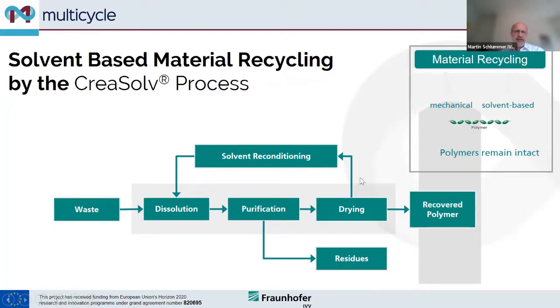Solvents are kept in a circle, and of course, purification means we always have a leftover. Leftover could be something which is not reused, but in our case, we try to make use of that. So if we go with a multi-layer packaging, we first try to get out the polyolefins, PE, then PP. Then we also had it for PA and even for PET. In the automotive sector, we had PA and PP as an input, and the residues were carbon and glass fibers. And here the recovered polymers, of course, are polyamide or polypropylene.